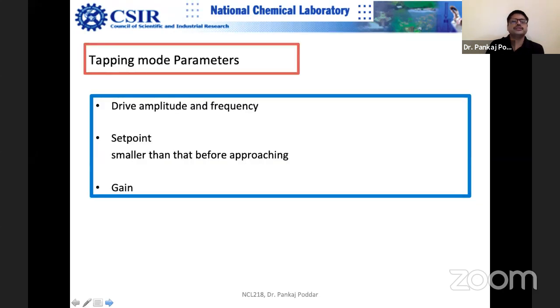So what you do, basically, you set the drive amplitude and frequency and also the amplitude set point. I'll give you the balloon example. You have to set how high you would like to fly the balloon, for example, 50 meters away from the surface. So here we set the amplitude that we want to maintain. This is the amplitude set point. If the amplitude goes lower than this, just raise the tip until the amplitude becomes normal, whatever my set point is. If the amplitude becomes higher, that means the force is dropping. Why is the force dropping? Because you are going quite high, the tip to sample distance is larger. That means your force is weaker, so the amplitude is returning to its normal amplitude. So it is time for the feedback to lower the tip sample distance until you reach that amplitude set point. That is the logic, that is the feedback.